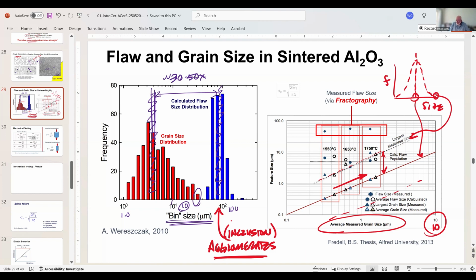But notice when they looked at their calculated flaw population, this is based on strength measurement. Okay, the flaw populations in this system all sit here. So they are narrowly distributed, but eventually they overlap, but they are constant in this system. In other words, my flaw population at 1550 is about the same as my flaw population at 1750. So there's no real change in the size of my flaw with increasing temperature. That's really important, and we're going to come back to that.